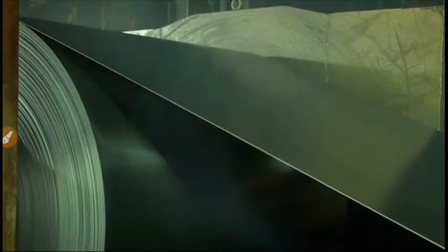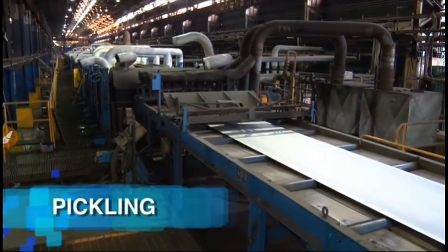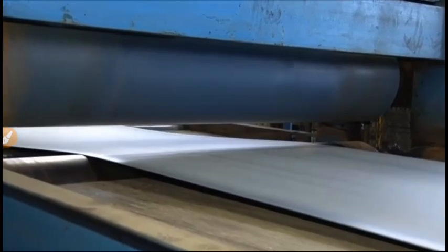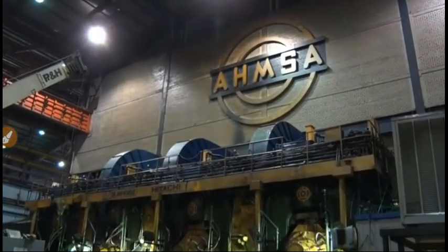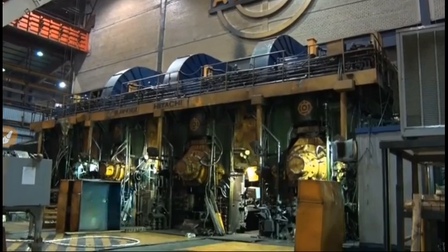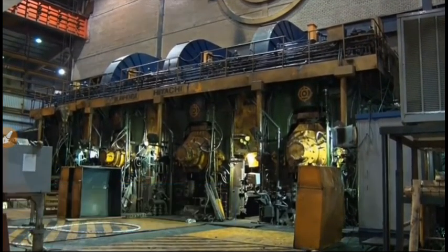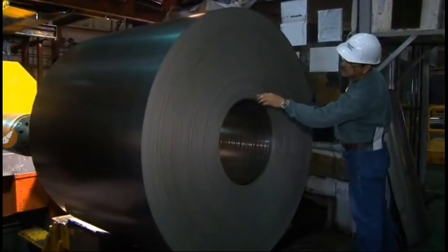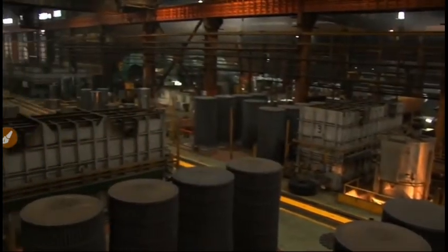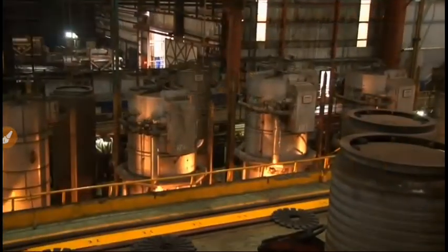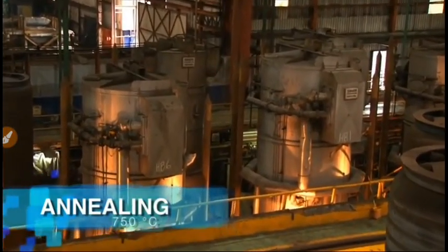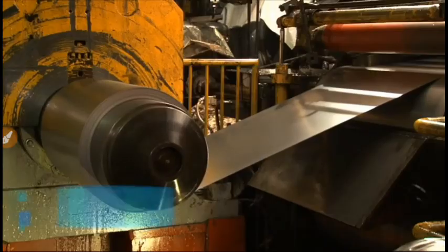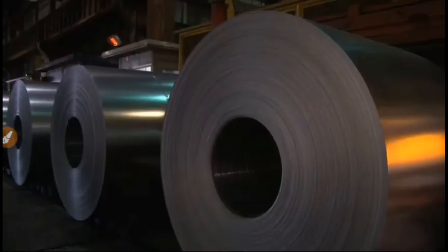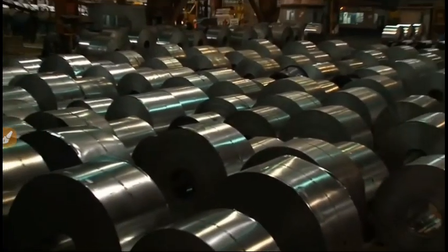Through cold rolling, the thickness of the sheet is reduced, while at the same time modifying and enhancing its physical properties. The process begins with pickling in order to eliminate oxides through the use of a hydrochloric acid-based solution. Then the strip is rolled at room temperature in various mills in order to gradually reduce its thickness and achieve the desired specifications. In order to soften the material, the coil is annealed in a continuous heating oven at temperatures of up to 750 degrees Celsius. The steel strip then goes to the tempering mills, which give it a greater surface quality and the specified hardness required for the various applications.